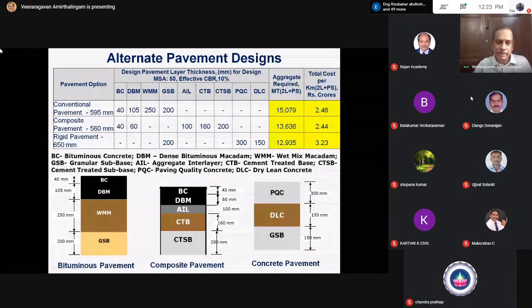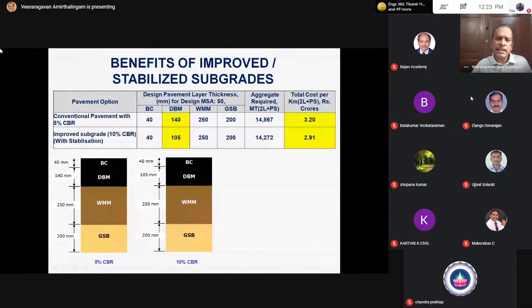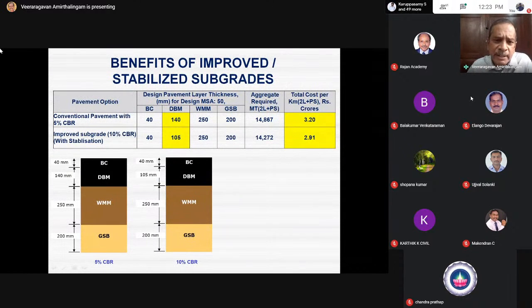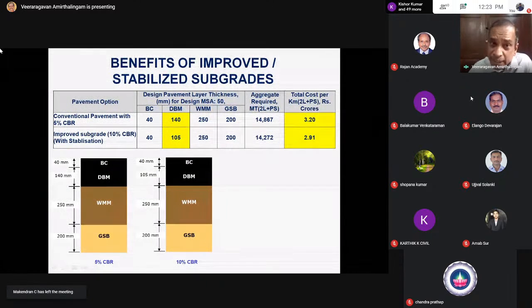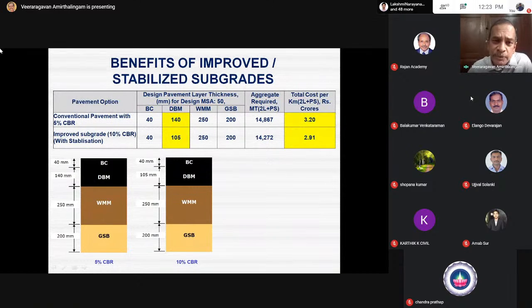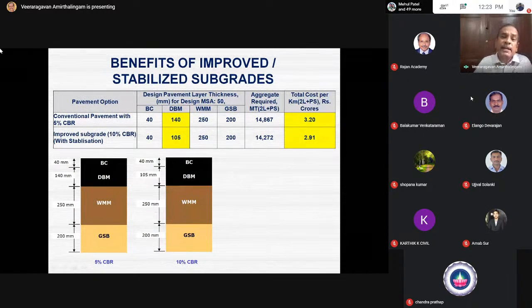I'll come to that issue. But you should consider alternate pavement designs. Simple. I want to improve the subgrade. So what are the issues? By improving the subgrade from 5 to 10 CBR, as per the IRC, you can reduce the thickness of the bituminous binder course from 140 to 105. From 3.2 crores, you can bring down to 2.91.